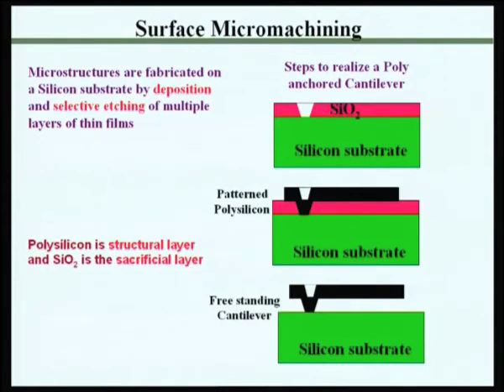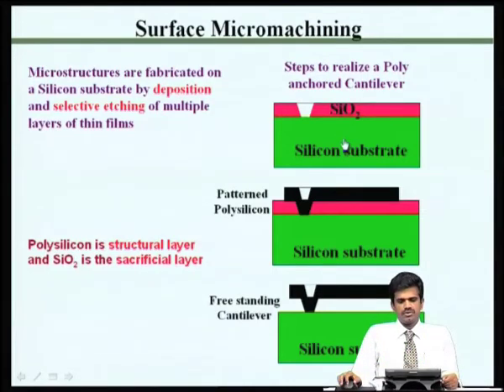We have also seen that by a choice of structural and sacrificial layer materials, we can build limited structures by using what is known as surface micromachining. In this case, we basically add layers to the surface of this substrate. For example, at the minimum, we will need to add one sacrificial layer which will eventually be removed, and a structural layer which will be retained as the moving part in microsystems. By suitable choice of materials, one can build several useful microstructures by this approach.